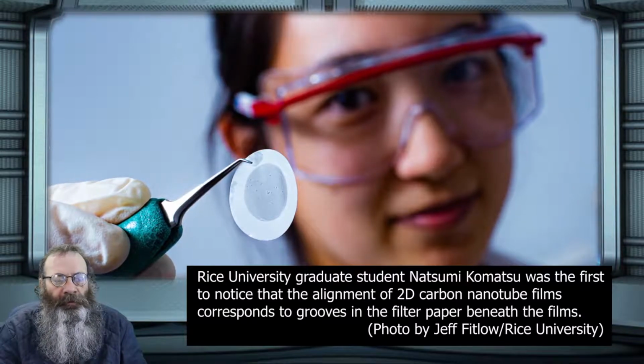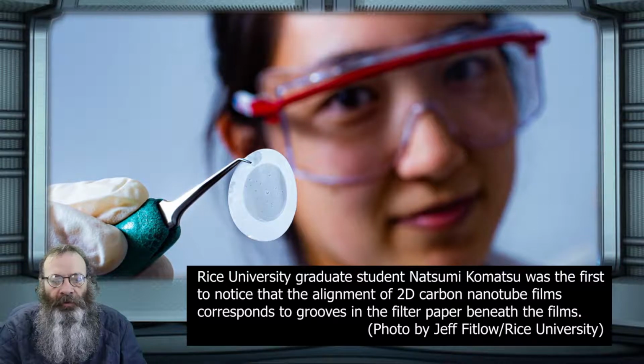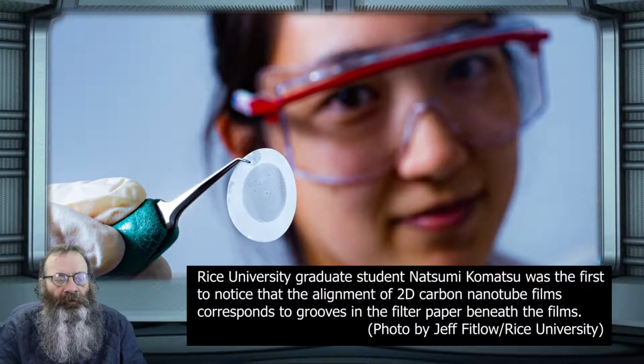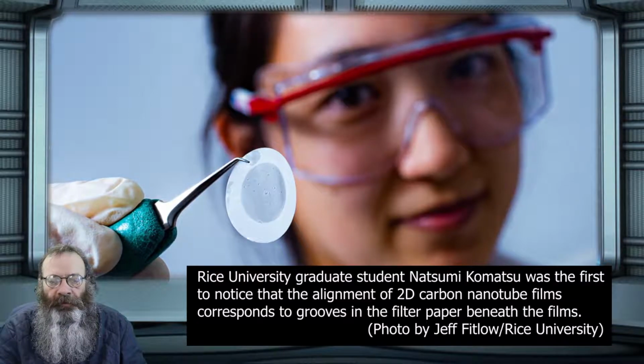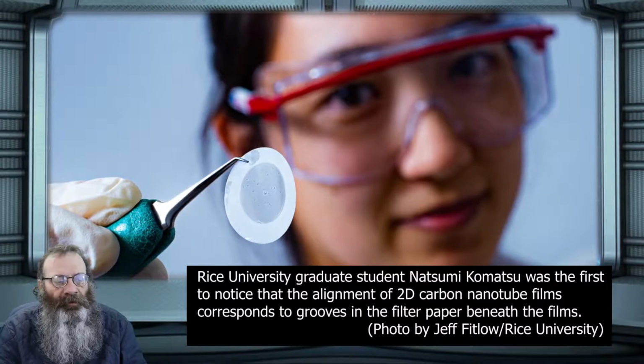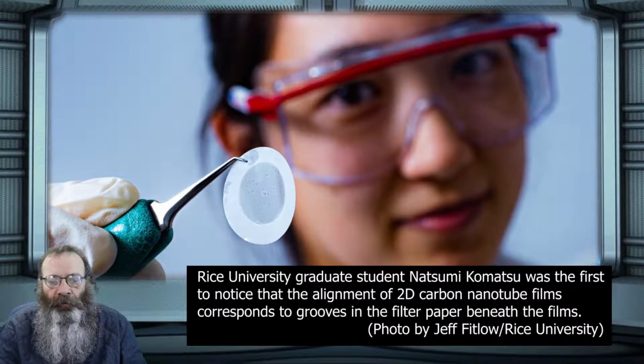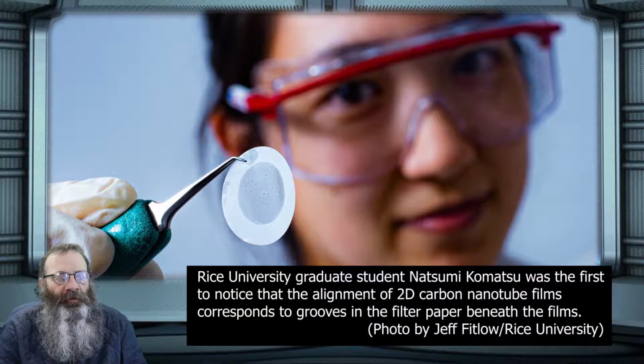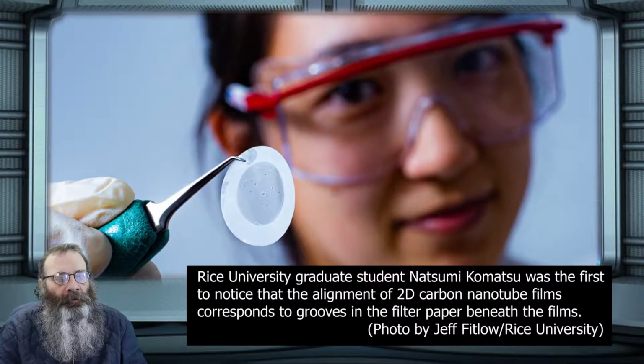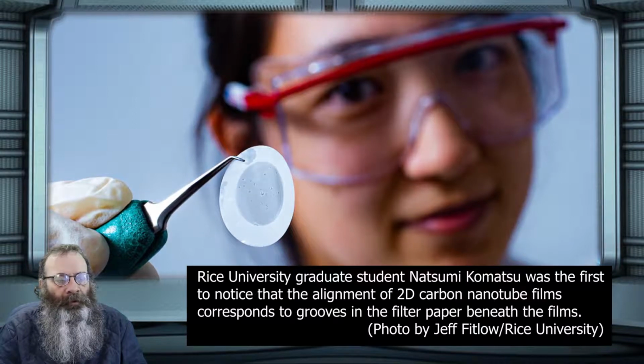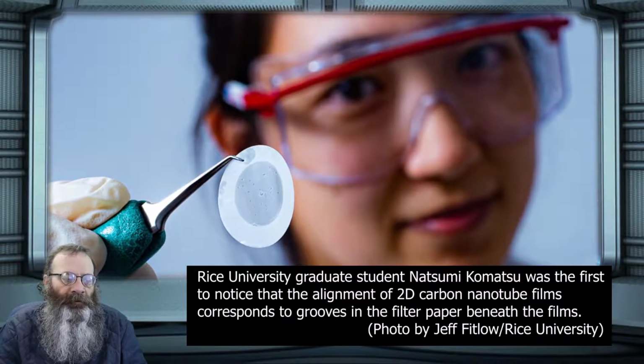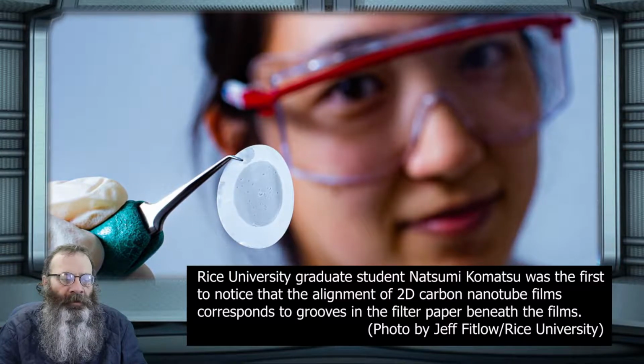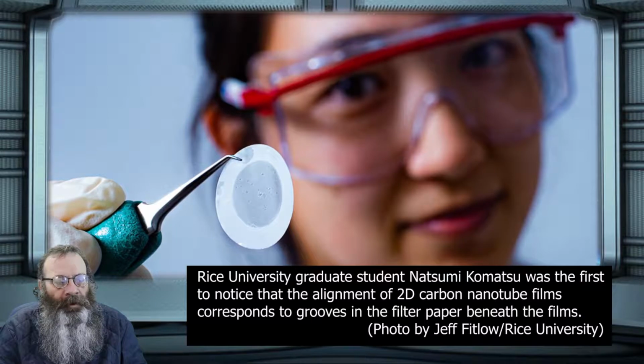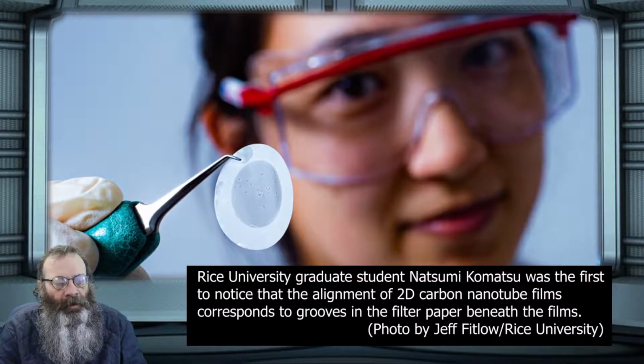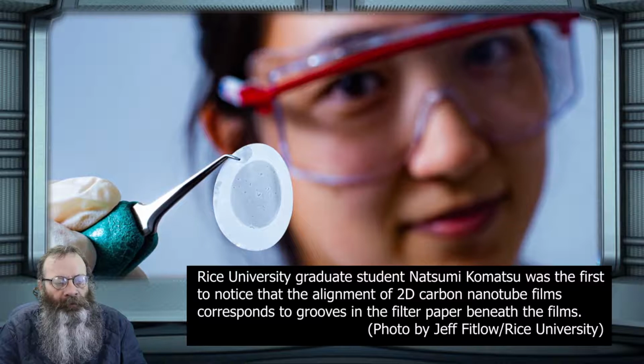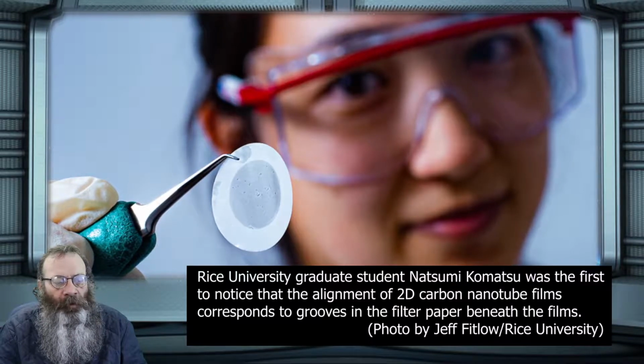Komatsu examined dozens of sample filter papers and used scanning electron microscopes and atomic force microscopes to characterize grooves and patterns of grooves. She cut filters into pieces, reassembled the pieces with grooves facing different directions, and showed they produced films with matching alignments. Komatsu and colleagues also used heat and pressure to remove the grooves from filter paper, using the same principles involved in ironing wrinkles from clothing. They showed that films made from groove-free paper had nanotubes aligned in several directions. Finally, starting with groove-free paper, they showed they could use a very fine reflective grating with periodic grooves to create their own patterns of grooves, and that corresponding nanotube films followed those patterns.